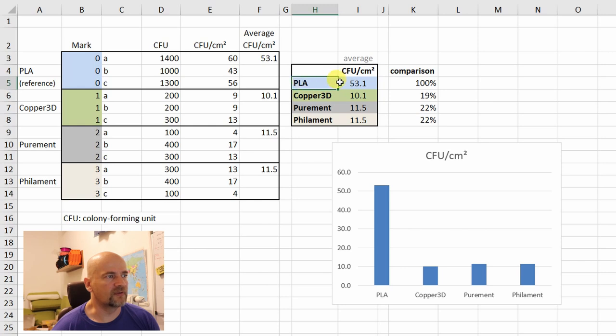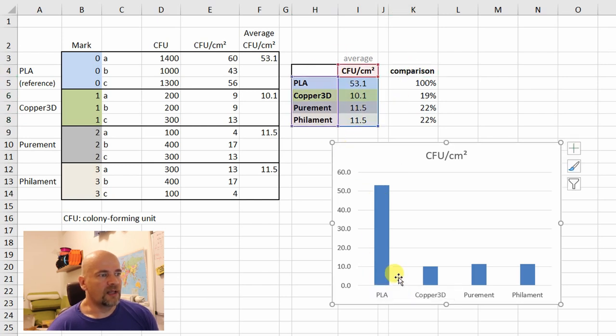So I summarize here the average values just for comparison. This is for reference ordinary PLA, and these three are antibacterial filaments. And also you can see these results in this table. Approximately 4 or 5 times bigger were the CFU per square centimeter with the regular PLA. So the effect of the antibacterial filaments is obvious, but as you can see from this number, from a food safety aspect, it's not perfect.